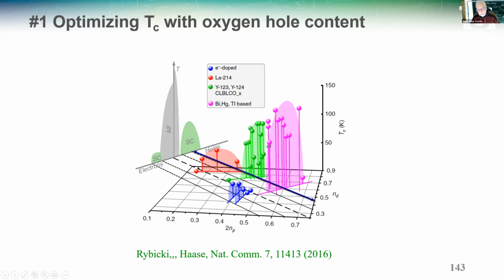The domes that are here are for different compounds or different families of compounds. What this is meant to illustrate is that for one hole doping, you can get many different TCs. But what quantum mechanics tells you is that if I put one hole in the unit cell, it has a probability of being on copper and a probability of being on oxygen. Now you could use either axis here, but there's a clear trend: if I look at the maximum transition temperature, I forgot to say that this vertical scale is the transition temperature. It's a busy plot. One needs to go a bit slower perhaps than what I'm doing.